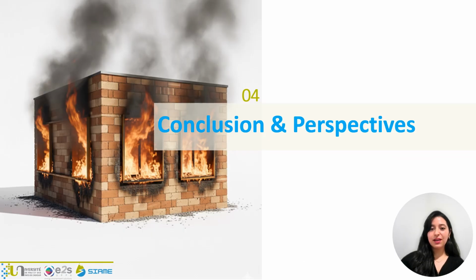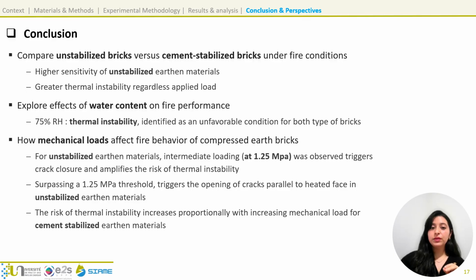Finally, based on these results, I will conclude with key findings and share some perspectives for future research. To conclude, our study gives a comprehensive idea of how fire affects compressed earth bricks under different moisture and load conditions. First, comparing the two brick types, we see that unstabilized earthen bricks are more sensitive and show greater thermal instability than cement-stabilized bricks, regardless of the applied load. Second, regarding water content, 75% relative humidity stands out as the most unfavorable condition for both brick types.